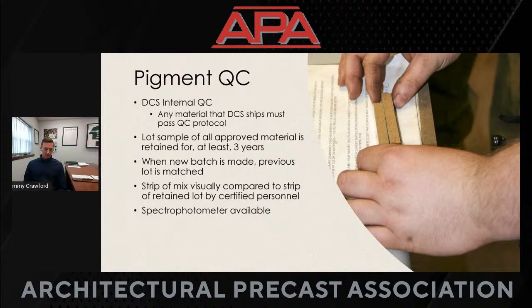I talked a little bit about our internal QC program, but any material that DCS ships must pass our internal QC process. We keep lot samples of everything that we've made for at least 3 years. Every powder, liquid, and granule that we send, we keep a small jar of in our lab so that we can pull that out if there's ever a problem, or if we need to make another lot to match that. We check it against the new mix that we're making. As you can see, Tim, our plant manager, is visually inspecting those 2 strips to make sure that the lot matches the new mix.